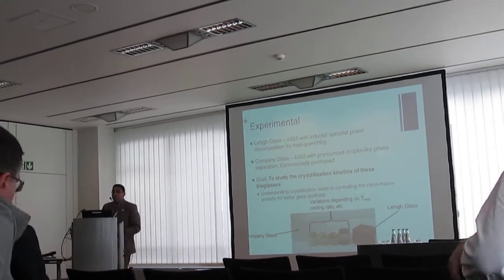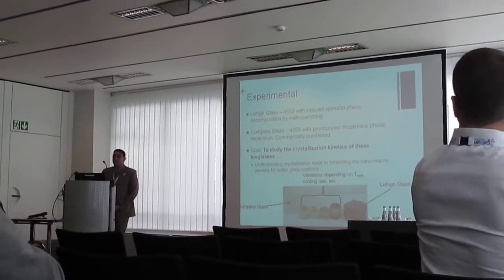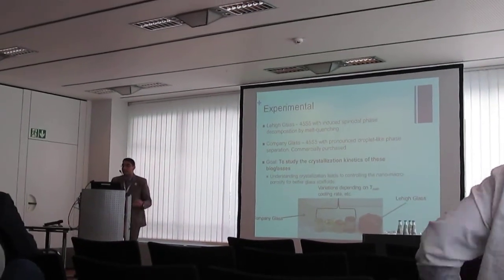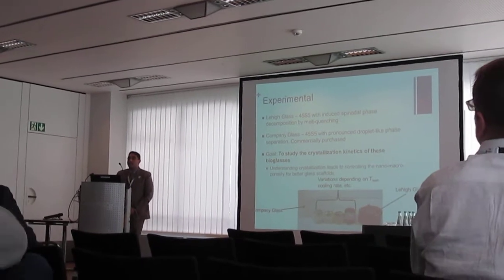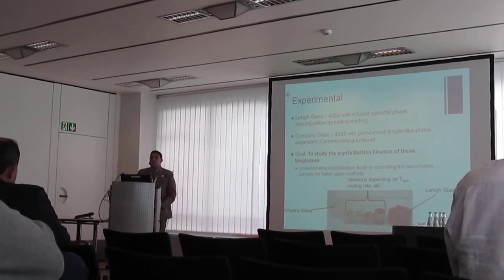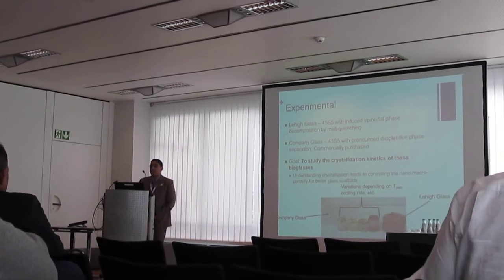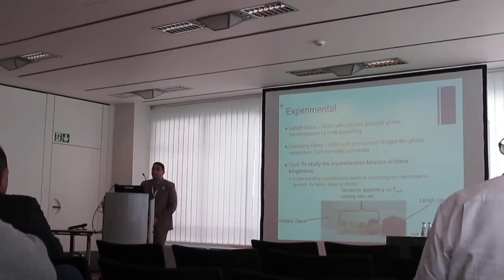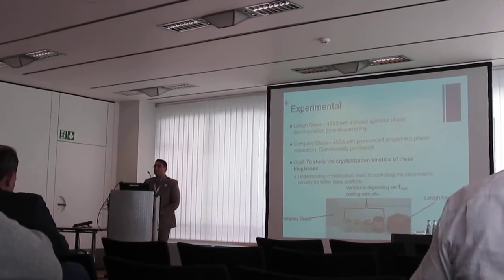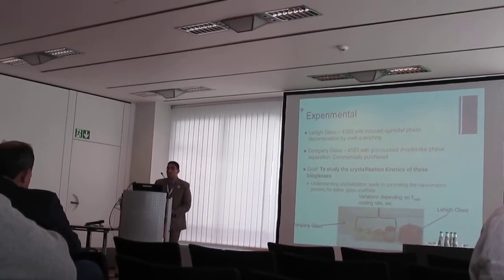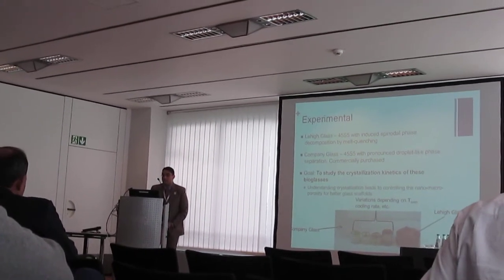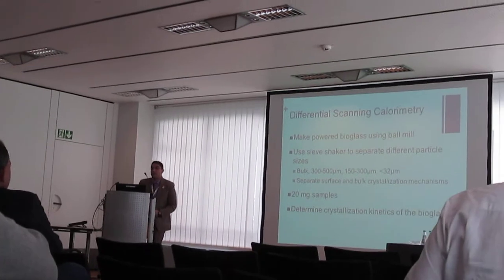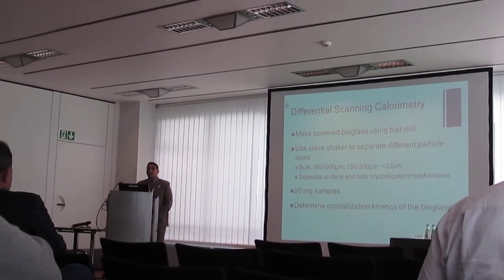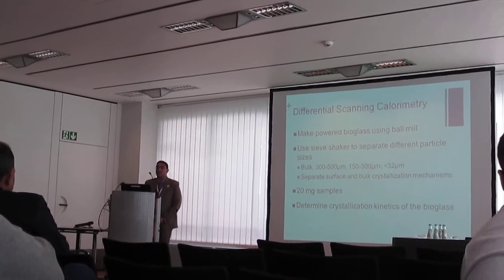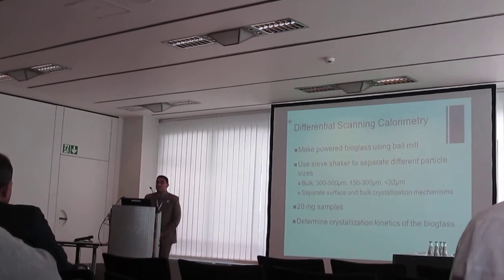We wanted to study the crystallization kinetics of these two bioglasses, the Lehigh glass and the company glass, because understanding the crystallization leads to controlling the porosity introduced when the glass is heat treated for creating bioglass scaffolds. The method we used for this experiment was differential scanning calorimetry.